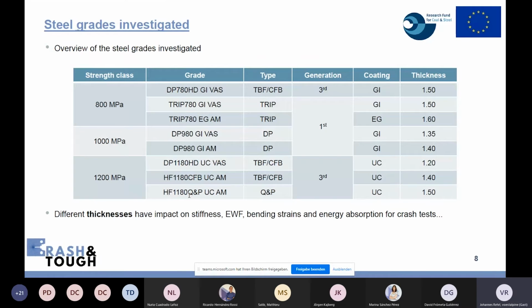This table gives you an overview of the steel grades investigated in the project. So we had three strength classes: a class with 800, a class with 1000, and a class with 1200 megapascal. In the class with 800 megapascal, we had two TRIP steels and one TBF/CFB grade. In the 1000 megapascal class, we had two dual phase grades. And in the class with 1200 megapascal, we had two TBF/CFB grades and one typical Q&P grade.